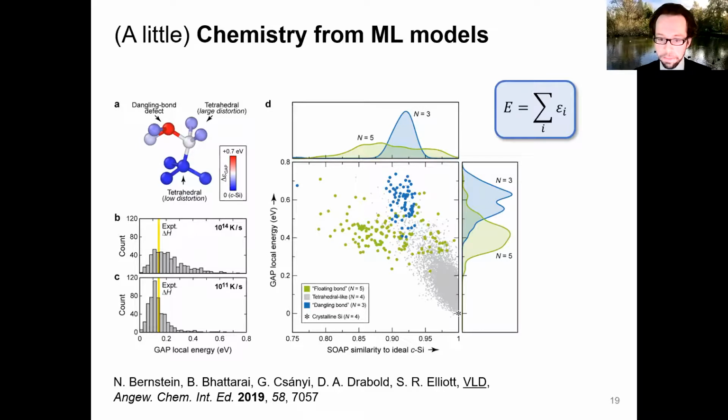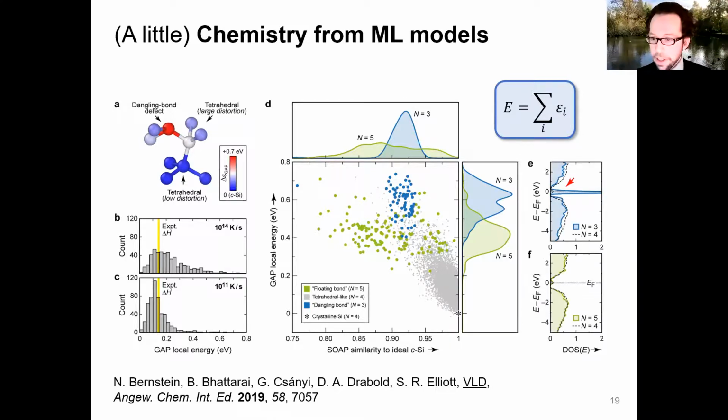This is why, in fact, these structure models are slightly more stable than the WWW model in DFT computed energies. And you can look at these distributions and see where it comes from. You can link this to electronic analysis, these electronic densities of states. And again, for the threefold atoms, if you're projecting onto these atoms, you have high density of states at the Fermi level for those threefold atoms, and almost none for fivefold atoms in properly relaxed amorphous silicon. So we can go back and extract some information about local environments and try to understand better what is the stability of these phases.